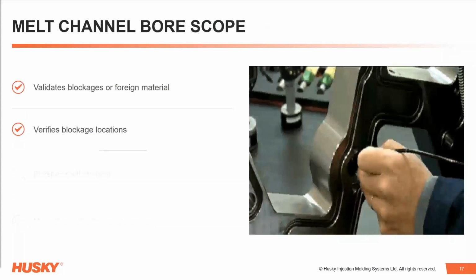The manifold is then bore scoped. A tiny, flexible cable camera is inserted and probed through the melt channels. If any blockage exists, it can be quickly identified. This can also identify areas with a high amount of erosion and confirm melt channel plug quality. If any issues are observed, repairs and replacement can be proposed.